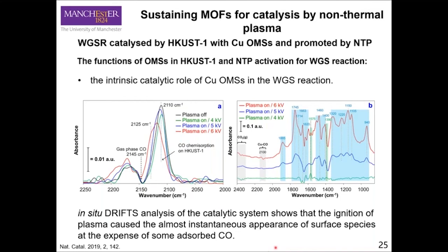So therefore, we developed an in situ drift cell and show, as you can see, when we have the plasma on and increase the applied voltage, we can clearly see the surface of the catalyst changing. And those changes tell us the information about the surface evolution of the intermediates and the products, etc. So by using this in situ work, we prove that this is indeed a catalysis, a catalyst facilitated by a good catalyst under plasma condition. This is quite important.